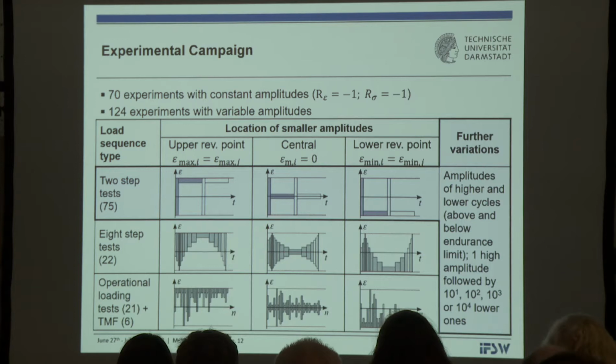So the load sequence we are interested in, I already introduced it. It is shown in this table here, in the middle of the last line. So this is a pseudo random sequence associated with the spectrum I've shown. And what we did is that the small cycles are not interspersed only in the middle between the largest and the lowest strain, but we also hung them up on the upper reversal point, or shifted them to the lower reversal point. We took the spectrum and applied it in an ordered manner, going upwards, downwards, upwards, downwards, again shifting smaller cycles up or low in order to identify the effect of mean stresses.